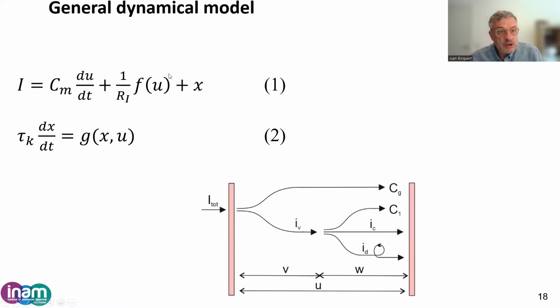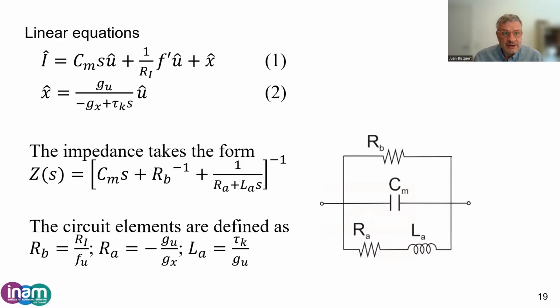So to the memristor equation, here I add the capacitive charging that is always at the interface or by the bulk capacitance. And then we have this structure with a variable x that has a separate equation. And this is the model for the chemical inductor, whatever the interpretation. Here is current voltage, but x can be many different mechanisms: in chemical reaction, in recombination, in corrosion, etc.